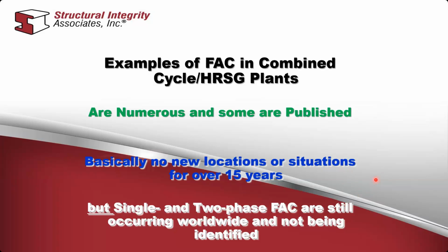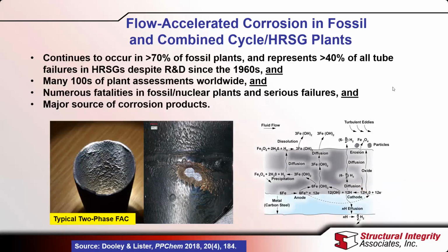And the importance is that each one of these mechanisms, single and two-phase, are dealt with differently from a chemistry point of view. You can switch them off by different aspects of the chemistry. So it's important that you identify exactly which mechanism you have. This just provides you a little bit of statistics, which will become clearer on the next slide. This is two-phase FAC at the top of the LP evaporator. And FAC, as it says here, continues to occur and represents more than 40% of all the tube failures in HRSGs, despite a lot of R&D since the 1960s. And down here, you can see a little explanation of how FAC takes place. If you want to see it in detail, you can see the latest paper.